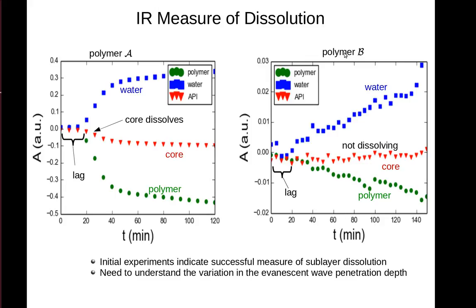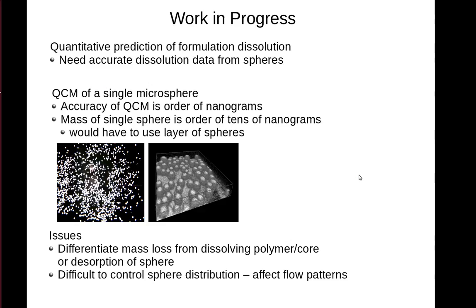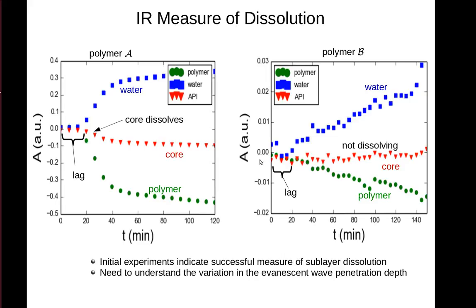Conversely, if we look at Polymer B, we see that after the initial lag there's the increasing of water. However, if we look at the scales, we see that the absorption is approximately an order of magnitude lower than Polymer A. That makes sense since this polymer is a bigger barrier. Also, we see that there's a much slower dissolution rate of the polymer relative to the water compared to Polymer A.